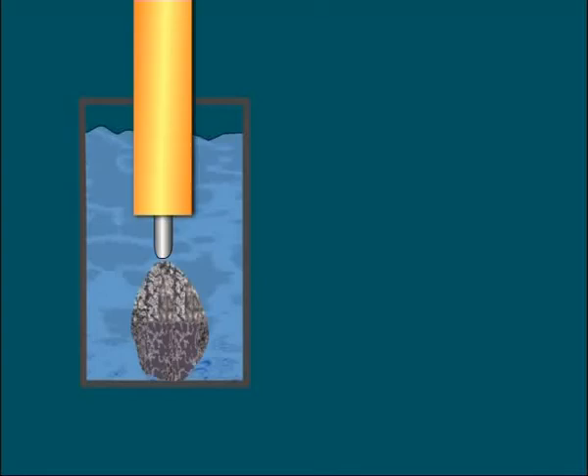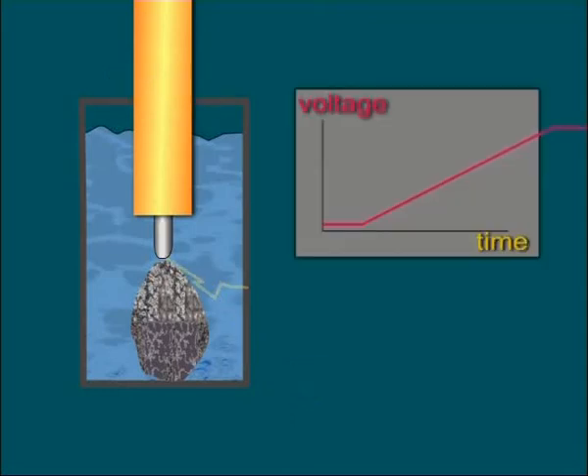A few words about the process. High voltage pulses of up to several hundred kilovolt are applied to the material between a high voltage electrode and the grounded walls of the pool. When the voltage pulses rise slowly — let us assume within milliseconds — most of the discharge will pass through the water and only part of it through the material. When the pulse voltage is made to rise more and more steeply, most of the discharges run through the material, not through the water.